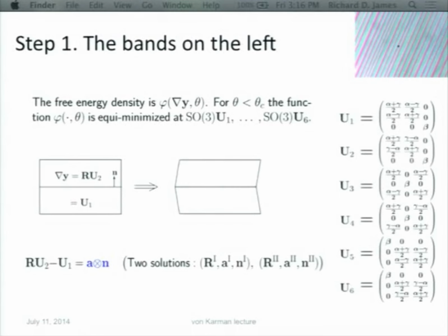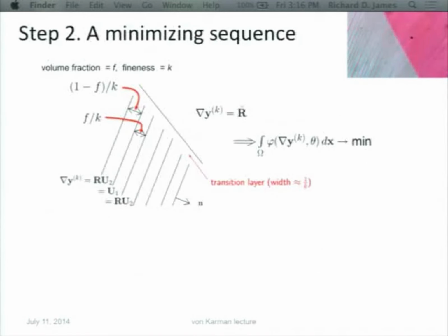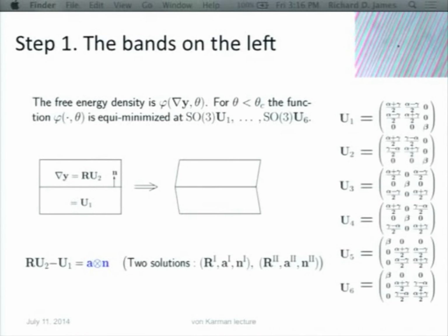And that, to have a continuous deformation, a necessary and sufficient condition is that these two matrices differ by a rank 1 matrix. So these are given. R, A, and N are unknowns, and there's an algebraic problem, you work it out, you get two solutions. And you compare with that picture, even at an atomic level, and it agrees very nicely with those two solutions. So you have very nice agreement with the normal to that interface, and the shape changes even at atomic level.